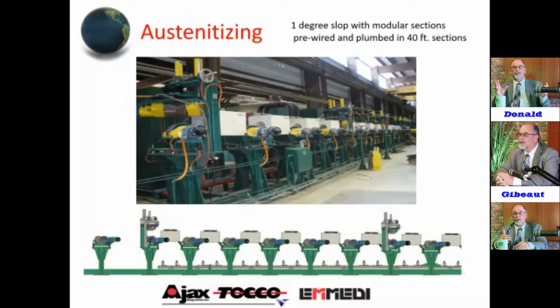And when you're heating the pipe to 1850 degrees, water spraying on the inside there is going to thermal shock and break the aluminum refractory out. So here's a typical line. This one is rated at 36 tons an hour.